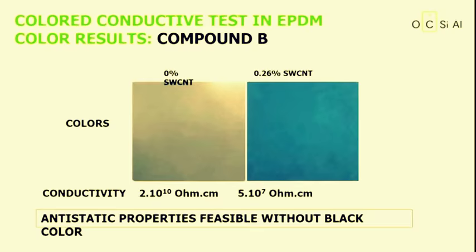So this is the kind of color we could get by adding 0.26% of single-walled carbon nanotube. As you can see, conductivity increased, resistance decreased from 2 × 10^10 ohm to 5 × 10^7 ohm. So now, it was possible to have colored antistatic or conductive compounds.